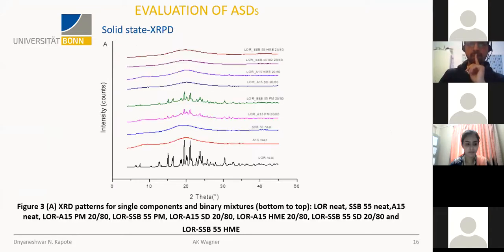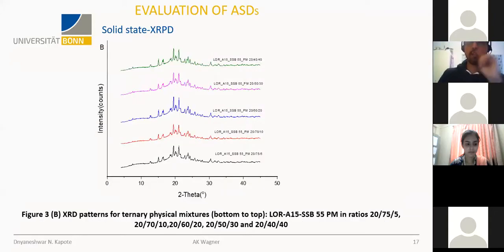Then another proof of confirmation was XRPD. With XRPD, the black one stands for the loratadine neat, while the red and blue stand for Affinisol and shellac, which are completely amorphous. In the case of the ternary physical mixtures, we can clearly observe that the crystalline peaks were appearing, which is comparable with the loratadine API, indicating that they exist in crystalline form.